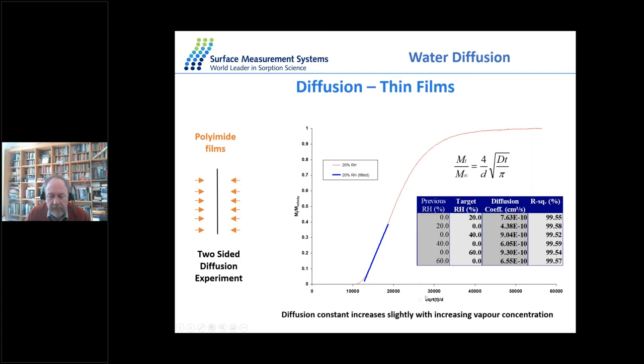and of course we get an increase in mass. And if we plot the mass at time t over the mass at time infinity against the square root of time, we get a very standard sort of diffusion analysis, which allows us from the slope of this line to measure the diffusion constant. So if you're interested in diffusion in materials, and in this case in thin films, if we know the thickness of the film, there's a very simple way we can determine the diffusion constants. And here are some diffusion constants at 20, 40, and 60% humidity for some polyimide films.